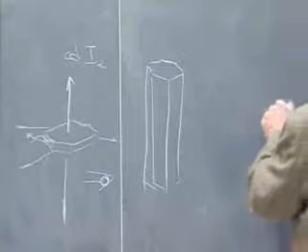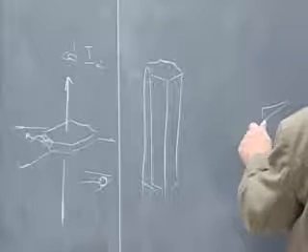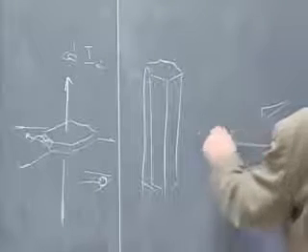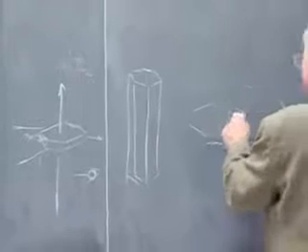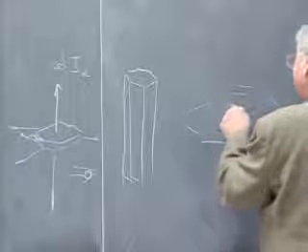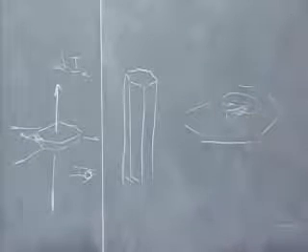So the original postulate, and now we all take this for granted, is that if there was a flaw such that the crystal developed a dislocation on this surface and it exposed a ledge, atoms would accrete and stick more tenaciously to this exposed ledge of the dislocation.